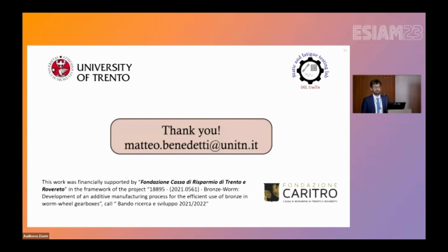But you need to take into account that we are not depositing pure copper. We deposit bronze that contains 10% of tin. This helps a lot to reduce the reflectivity of the powder. So I don't think that we need to change laser source in this case. In case we were depositing pure copper, then I agree with you. We should change the laser source. We have a project running now with the National Institute of Physics in Italy, in which they need to deposit pure copper. And in this case, we will opt for green laser sources. Thank you for your question.